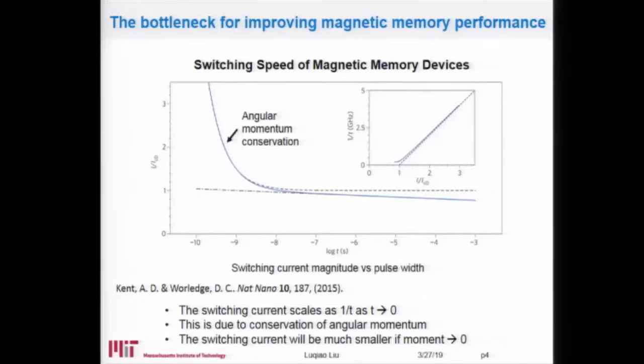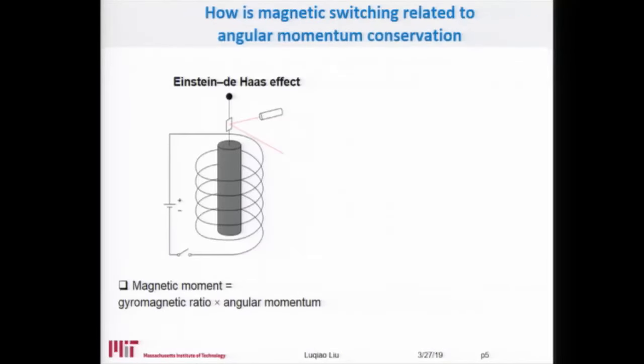But here, we can at least see that there is a very sharp increase in the switching current as you reduce the switching pulse width. This actually turns out to be governed by a very fundamental physics law, that is angular momentum conservation. So why do I say this? Why is the switching of magnetic moment governed by angular momentum conservation? It has something to do with the nature of magnetism. And we know magnetism is nothing but angular momentum.